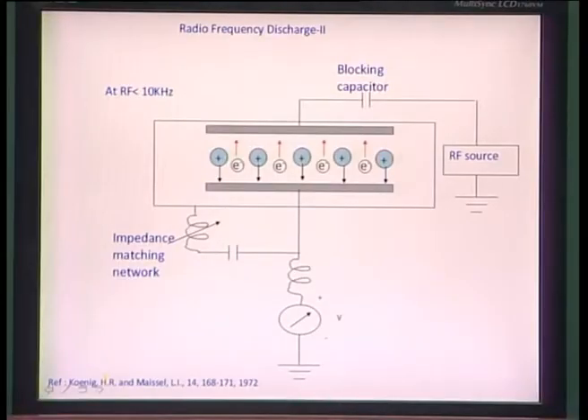So as I told you before, this blocking capacitor ensures that the RF source 100% feeds the voltage supply onto this parallel plate system, and here you have these ions and electrons, as you are seeing, species which are made within the plasma chamber. Now if you actually go ahead and couple the RF source onto the plates, there is almost always a change in polarity with the RF signal. So for half cycles this plate may be positive and this may be negative, and for the other half of the cycle this may be the opposite behavior.